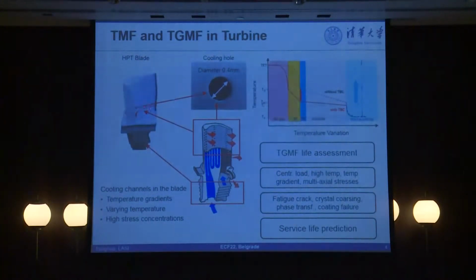Therefore, we have to cool down. We introduce cooling air into the blade and the cooling film and so on to keep the material temperature lower than 1,000 degrees C. That is the absolute maximum we can work at. Therefore, in such a part, we have very large temperature gradients in the component. It's not only around the hole, but also within it. And the stress in the blade is not high, but we have temperature coupled with mechanical load. Therefore, the problem is coupled thermomechanical loading with additional temperature gradients. That is the case.